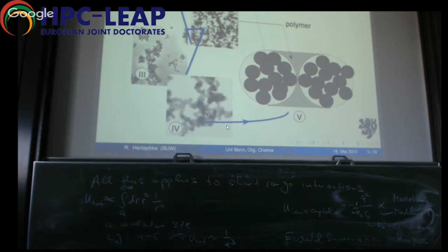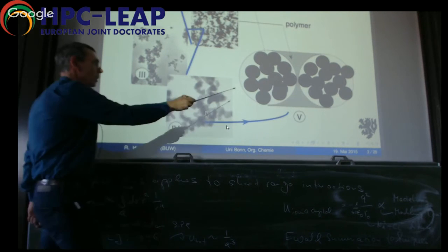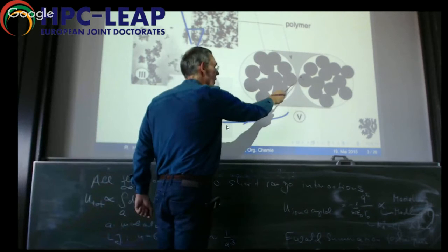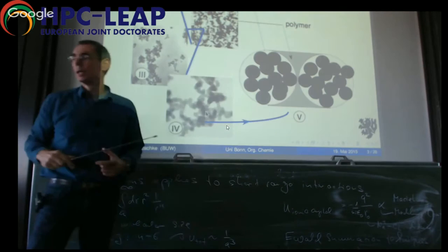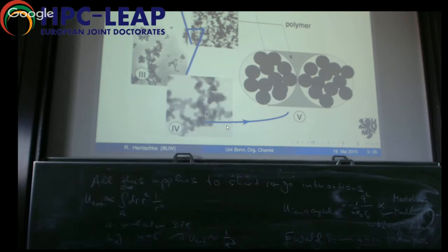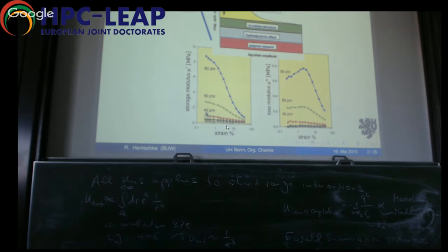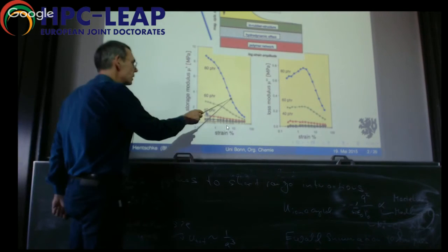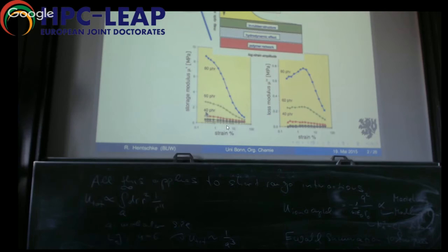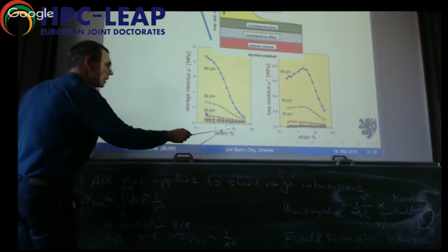And this kind of breaking of contact, where these two pieces are pulled apart, that is the internal friction that you were mentioning. So this is actually internal friction that leads to the decrease of the spring constant. And unfortunately, that decrease is not coming back when the strain is released.